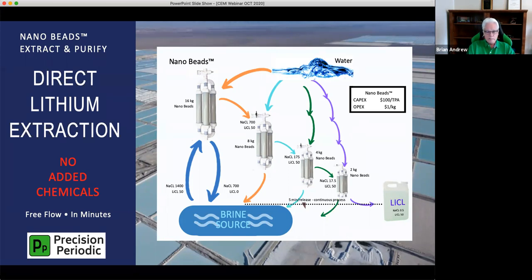In this case, we're releasing the filter with water. And so no acids needed. And so that's quite a good process to use. Again, it comes down to your competing elements. In this case, the salt is 110,000 parts per million, and the lithium is only 400 parts per million. So you're going to get salt whether you like it or not. So it's a case of just optimizing the filter to prefer the lithium and then cascade it. And each cascade is a smaller set of filters. And by the end, you've got rid of all your salt, leaving just your lithium.